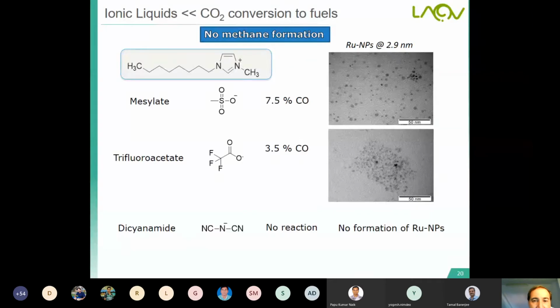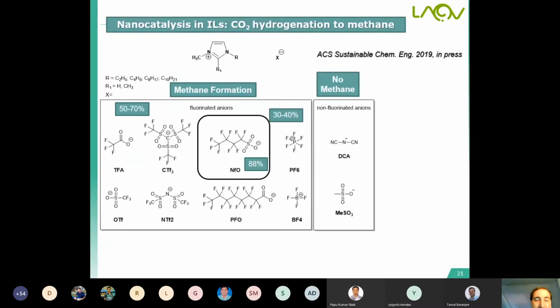In some cases, no methane was observed, like using mesylate, trifluoroacetate, or dicyanamide anions. In the first two cases, only CO. In the last case, no reaction because no formation of ruthenium nanoparticles. This means it's possible to perform nanocatalysis in ionic liquids, and in particular CO2 hydrogenation to methane. And in this case, we are using imidazolium cations and different kinds of anions, fluorinated anions. This is crucial for the methane formation, and nonaflate is the best.